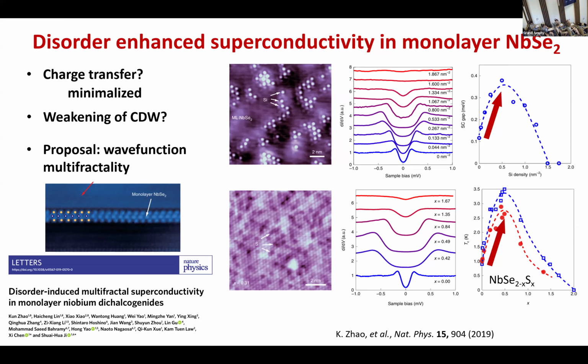Do you have a sort of understanding why charge density waves would suppress superconductivity, or what would be the mechanism? I would say that, just naively speaking, the charge density wave and superconductivity both take the same amount of charges. So the charges need to choose one thing: either they go to the charge density wave or they go to superconductivity. If all of them go to the CDW, then there's no charge to do pairing. So in that sense, I think they are kind of competing. But this is one way of thinking about this. I think some people also argue that CDW comes from electron-phonon coupling, and electron-phonon coupling can also help superconductivity. So they are actually enhancing each other instead of competing. So I think this is still quite under debate.